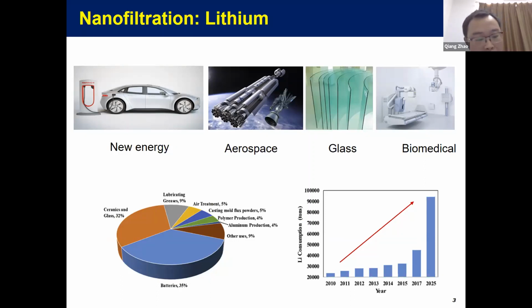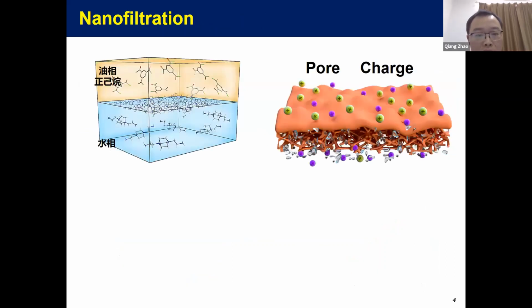But the main problem for China, like was said in the previous talk, is the high magnesium to lithium ratio. And when we are talking about nanofiltration membranes, most of the membranes currently, in addition to some new rising technologies such as layer by layer mentioned in the last talk, the dominating one is still interfacial polymerization, in which the acyl chloride monomers dissolved in the organic phase will react with amine or hydroxyl containing monomers dissolved in the aqueous phase to form a very thin layer, probably 10 to 200 nanometers.